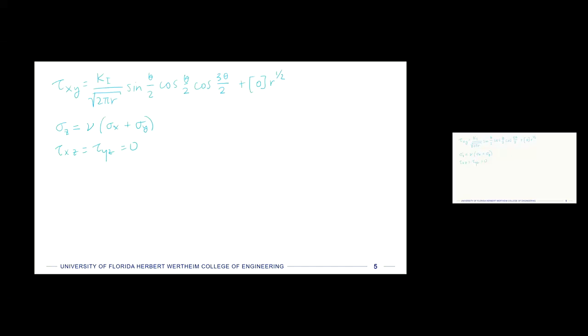Okay? So I mentioned before that the capital K, these factors, fracture toughness, this K1, K2, K3, can be thought of as kind of concentration factors of how a far field stress is affecting the near field and how that's going to lead to crack propagation. And so we are going to define the K here. All right, K is equal to an equation that has the form of stress times the square root of the length of the crack, right? So I mentioned that the fracture toughness had these weird units of pressure times square root of length. And so it comes from the definition of this form here.